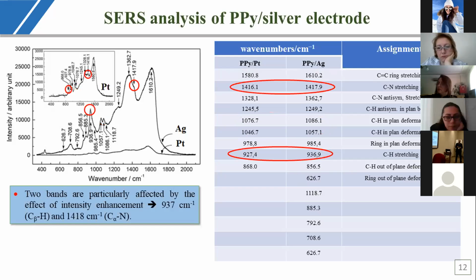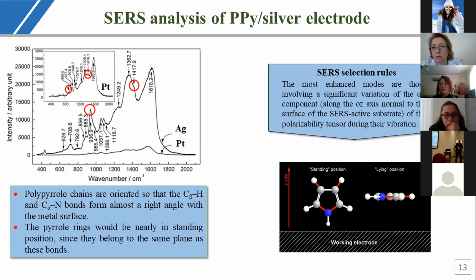In addition, 2 bands are particularly affected by the intensity enhancement. The band at 937 cm-1 is attributed to C beta-H, and the one at 1418 cm-1 is assigned to C alpha-N. According to the SERS selection rules, the most enhanced modes are those involving a significant variation of the alpha ZZ component of the polarizability tensor along the OZ axis normal to the surface of the SERS active substrate during their vibration. We can conclude that the polypyrrole chains are oriented so that the C beta-H and C alpha-N bonds form almost a right angle with the metal surface. So the pyrrole rings will be nearly in standing position, since they belong to the same plane as these bonds.